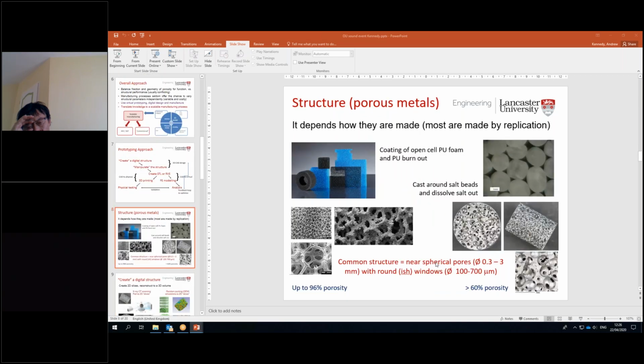Oops, I hopped right back to, yeah. So it makes sense to look at what the actual structures of porous materials are at the moment. And commonly, they're either made by burning out a polyurethane foam. We coat a polyurethane foam and then burn out the residual polyurethane. That gives us these traditional open structures that look like traditional polyurethanes.